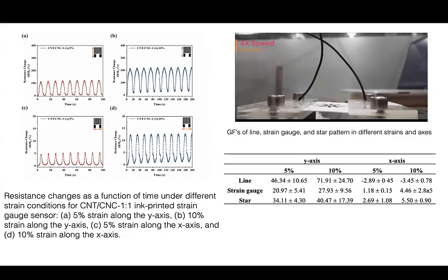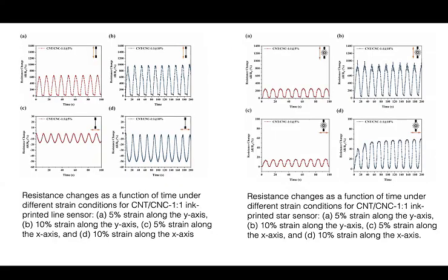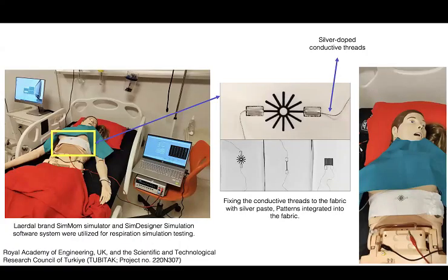It's not quite through tensile testing, but it also gives us a response in the longitudinal and transverse directions. Again, these are standalone structures. They are quite off-body. It's just to see whether we have quite repeatable breathing-like patterns once we simulate and program the actuation, and which sensor in which direction gives you a very good response. This is part of resolving the data.